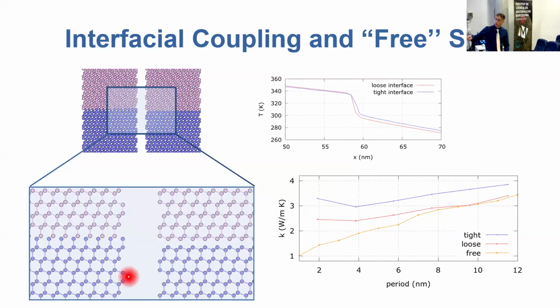Plus, we also asked ourselves what would have happened if we used a superlattice period which was not an exact multiple of the underlying lattice period. And in this case, the interfaces change in a sort of random fashion when we move along the superlattice. In this case, it is very interesting that the minimum does not appear. So there is no coherent regime for these superlattices. But this lack of a minimum is not observed in the experiment. It is rather unreasonable to expect that we have this degree of control in the experiment on the specific interface, but this is not observed, and we could not really assess why by means of our simulation.